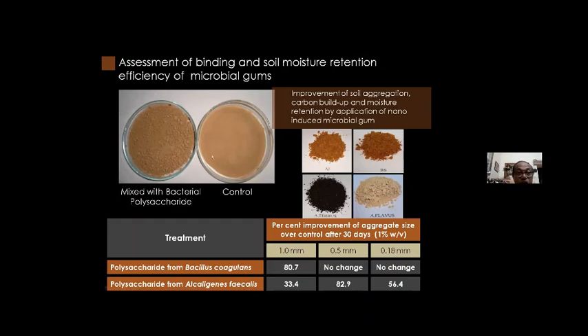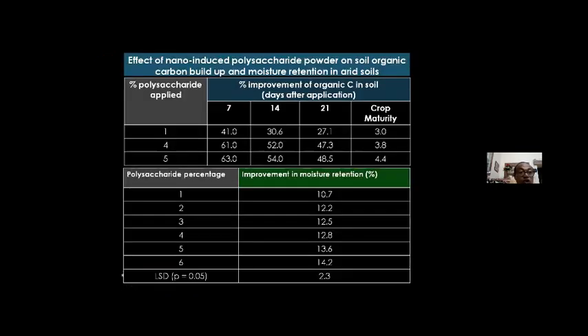You can see it here. This is Joshua soil, where 95% is sand particle. You see, within 1 month, how nicely they aggregated. So we are getting 33 to 80% improvement in 1 millimeter soil aggregate, 82% improvement in 0.5 millimeter, and 56% improvement in 0.18 millimeter. When we apply this at 1%, 4%, 5% in the soil, polysaccharide is a carbon, so immediately carbon buildup is there. But at crop maturity, you may expect at least 3 to 4% carbon buildup with the application of this nano-induced polysaccharide powder.